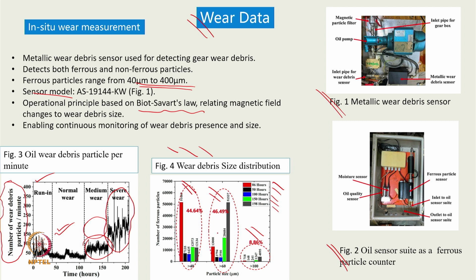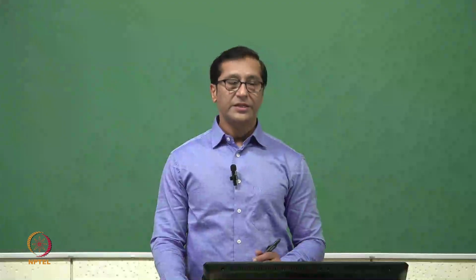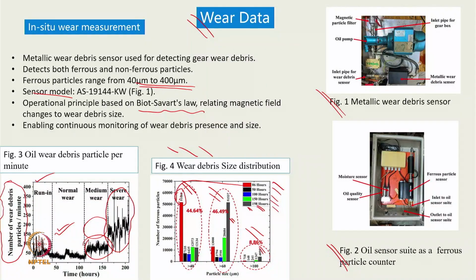Everywhere you can see the number of particles, particularly more than 60 to 100 micron, increasing at 198 hours. And even the more than 100 micron size is around 4000 particles after 198 hours. Initially we are able to see about 51,000 particles which come during the initial stage itself, of size more than 40 micron. Almost 50,000 particles we are getting after 6 hours itself.